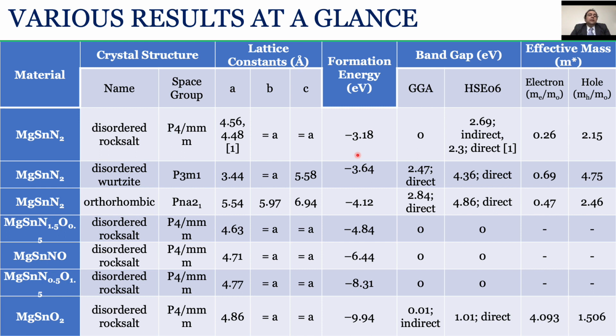Even though they are energetically metastable, we will see later that these two crystal structures are also mechanically and vibrationally stable. The value of effective masses for magnesium tin nitride in disordered rocksalt crystal structure is the lowest among these three crystal structures, which makes it best for charge carrier transportation.